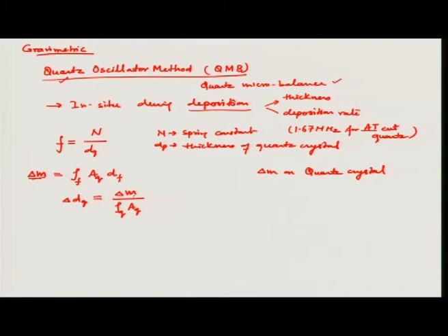So, you are saying how much the change in quartz thickness would be if the material being deposited was quartz. So, this is the quartz equivalent thickness. How much change in the quartz crystal thickness if the delta m mass being deposited was of quartz. This is not quartz, this is a thin film.